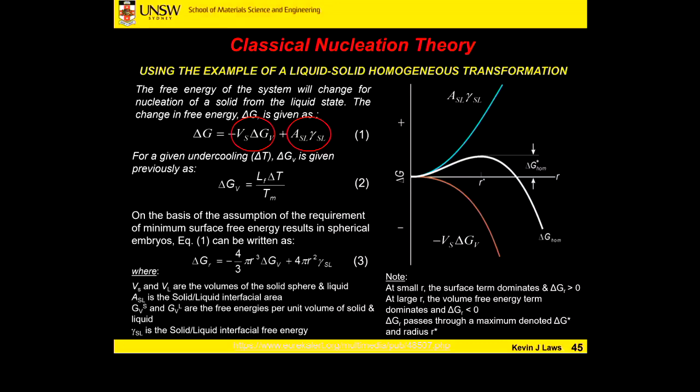For this to actually happen, this atom will have to move here, that one will have to move there, and that one there, perfectly and easily. When that happens, there's going to be a huge mismatch between the existing atoms in the lattice. Bond angles are all weird, their lengths are all weird. So that's a really high energy way to try to nucleate and grow. All right?